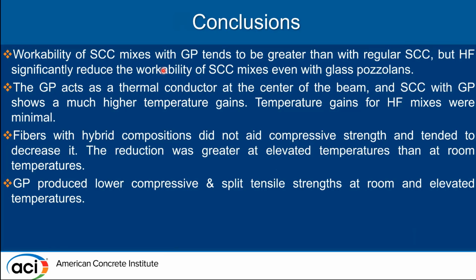Glass pozzolan at the core of the beam acted as a thermal conductor and resulted in very high temperatures. And the temperatures for the mixes containing hybrid fibers were minimal. It did not show any higher temperature gains. No benefits of adding hybrid fibers were observed for compressive strength, both at room and elevated temperature, and reductions were observed due to the presence of hybrid fibers for compressive strength.